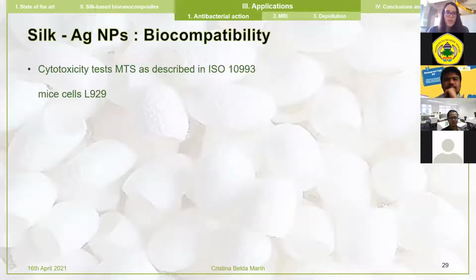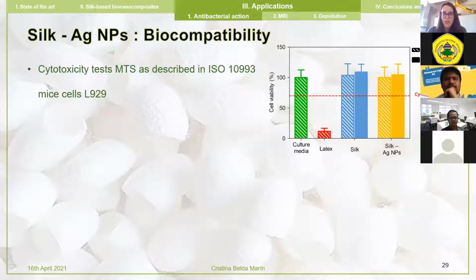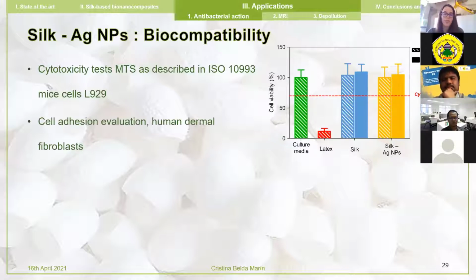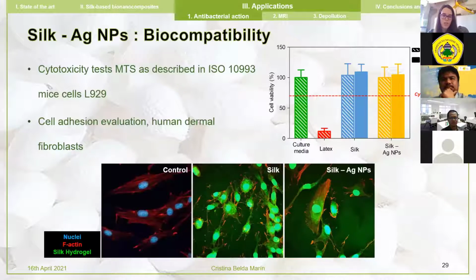Of course, these materials were tested to see whether they are biocompatible or not. And our cytotoxicity test, as described in the norms, showed that no cytotoxicity effect was observed. And moreover, human dermal fibroblasts were able to grow over the hydrogel in both conditions.